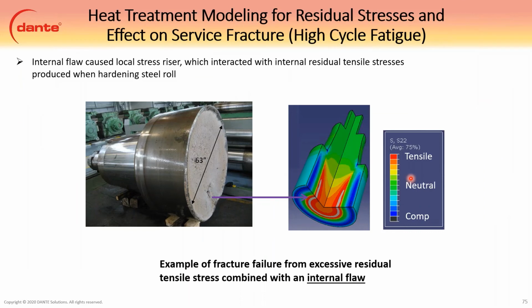This was one we looked at that had an internal flaw, a big, huge steel work roll. So we predicted high tensile stress in the location, but it took an internal flaw to actually make it crack. It wasn't that high.